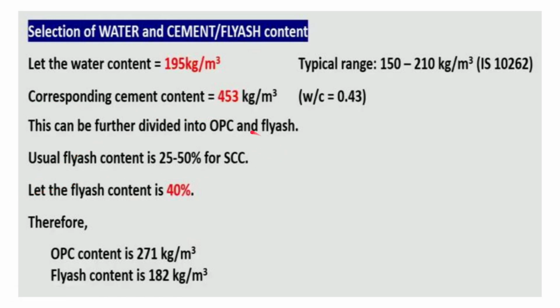Now if we are using OPC and fly ash, and we assume that fly ash is around 25 to 50%, we have taken 40%. So if we assume 40% fly ash and 60% OPC out of the 453 kg of cement content, then 60% of 453 comes to be around 271 kg per meter cube of OPC, and 40% of 453 comes around 182 kg per meter cube of fly ash. So 271 kg and 182 kg of OPC and fly ash is found, for a total of 453 cement content.